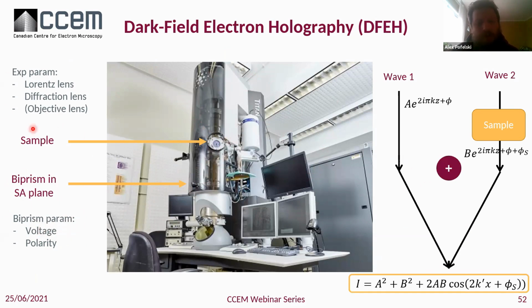Then after, what is very important to use is those experimental parameters on the top. So here I just put Lorentz lens. We use the Lorentz lens in this type of setup not because we want to have the objective lens off, but the idea is to increase the field of view. In this setup, different from some Hitachi microscopes, to have the larger field of view and a good overlap with your hologram, you need to go in this Lorentz mode. And after, you need to play with the diffraction lens to adapt the field of view of your hologram towards your sample. And that's usually the classic way of thinking about holography.